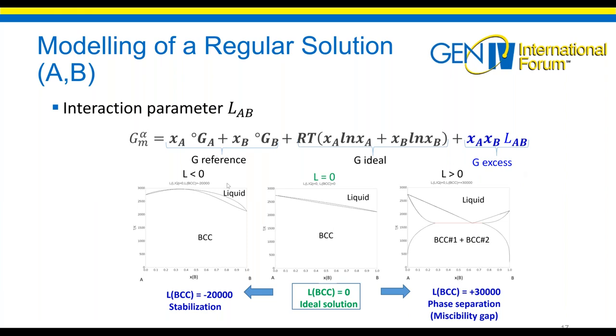And you can see on the different graphs that this interaction parameter is really, really important, because, for example, if you put a negative parameter, you have a stabilization. But if you put a positive parameter, you have a phase separation, and you can see that the shape of the curves are totally different. So phase separation with the formation of two phases, BCC1 and BCC2, the other two phases formed with a phase separation.